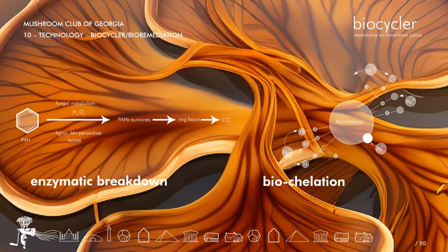There are a couple of ways fungi and biomaterials generally can be useful in this regard. There are petrochemicals in the built environment, things like bitumen and asphalt, and a lot of the treatments that go into wood. They have these polycyclic aromatic hydrocarbons, or different types of hydrocarbons, and you can get an enzymatic breakdown of that. Most of this crowd knows this, but the metabolism of fungi is external. They secrete enzymes out into their environment, which break down the material around them, and then they can take that broken down material and create their own biomass, or metabolize it into new materials. These hydrocarbons that were once woody materials still have a lot of the same chemistry and are able to be broken down by the enzymes that the fungi excrete for that extracellular digestion.